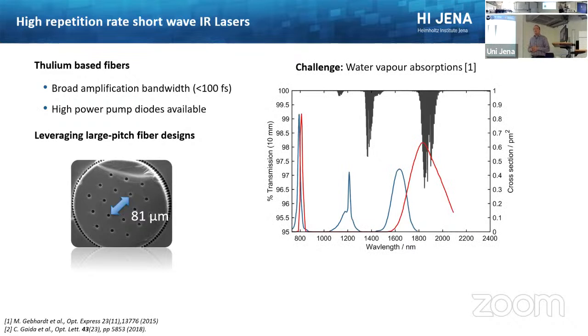One issue you have if you work at 2 micron is the absorption in water vapor. And you might think, okay, but I'm not operating near water, but even the water vapor in the air is enough to cause issues. So in black, you can see here the transmission and the absorption at different wavelength regimes. If you work at 1 micron, there's no issue. But if you go to 2 micron, especially where thulium emits, this red curve here, you are directly in this region of water absorption.